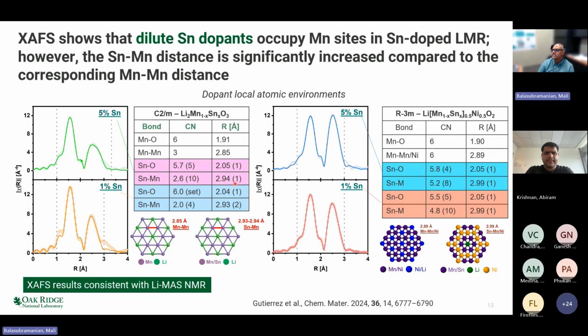So we believe that this significant increase in distance is one of the reasons as to why the tin allows us to strain the samples and create these small domains, which then end up having good kinetics and lowering the area specific impedance of the material in the highly lithiated, activated Li2MnO3 regions. So this is the sort of information that is very uniquely obtainable by XAFS. You can clearly understand oxidation states, and you can understand local distortions.